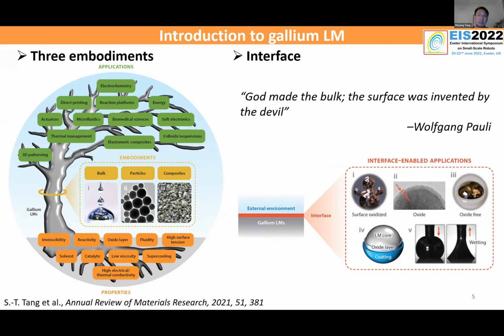But if you apply a strong acid or base, you are able to remove the oxide, so the liquid metal is going to bead up and let the surface tension dominate, so it's going to behave more like mercury. Also, on the surface of the oxide layer or on the liquid metal, we can coat macromolecules, including polymers or numerous other molecules, to bestow it with additional biofunctionalities. And the surface oxide also allows the liquid metal to wet a wide variety of substrates like silicon, glass, and gold.